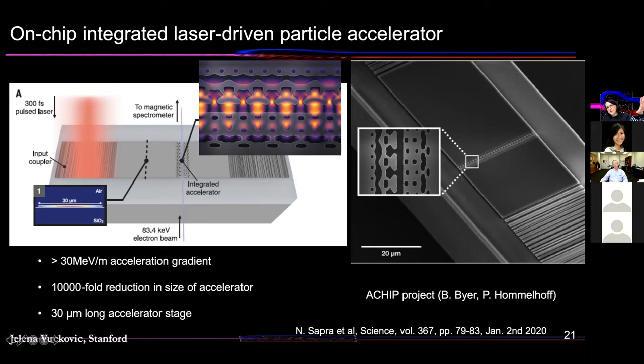And of course, this is just a single stage, 30 micrometers long. But as you see here, we were able to achieve 30 mega electron volt per meter acceleration gradient, which tells you that if you cascade 100 or 1,000 of these stages, you'll go to mega electron volts from 83 kilo electron volts, and you'll already get to the range of energies that are useful for material science and for medicine. And that's what we're doing now. We're cascading a lot of stages together.